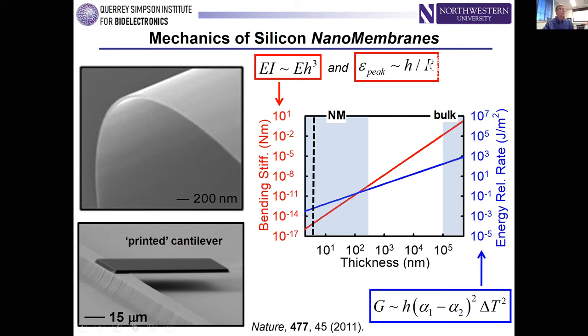But whenever you change a physical property by 15 orders of magnitude, it really has a qualitative impact on the way you think about the material. So a silicon nanomembrane is actually a very flexible, floppy object, not only because the bending stiffness is very low, but also because the peak strains associated with bending to a given radius of curvature scale down linearly with the thickness. So it's not only floppy, but it's also very bendable in the sense of the tightest bend radius that it can support before fracture. So that's a kind of trivial observation, but it turns out to be a pretty important one, because now you can create device-grade silicon in these nanoscale geometries and then use them as building blocks by integrating them onto a flexible plastic substrate or an elastomer slab to begin to build heterogeneous combinations of hard and soft materials engineered in such a way that the overall system-level properties are defined by the plastic or the rubber, only minimally mechanically loaded by the high modulus active electronic material, in this case, the silicon nanomembranes or nanoribbons.